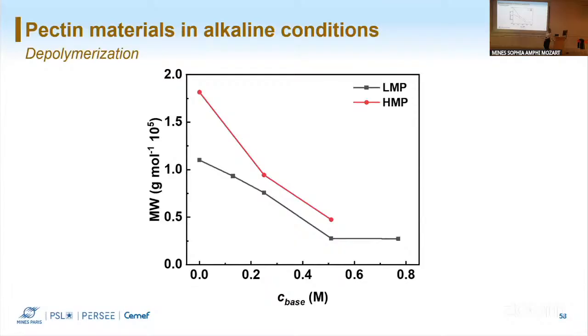And I think that the charge does not matter anymore in this system because you have such high ionic strength that you have a very strong shielding effect. But you do discuss the salting out effect. Yes. So how do you understand the salting out effect driving the gelation? Because of the ionic strength of the system, pectin is not soluble anymore in water in a system of that high ionic strength.